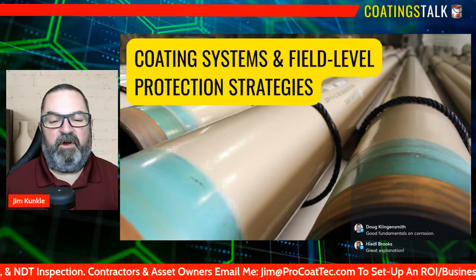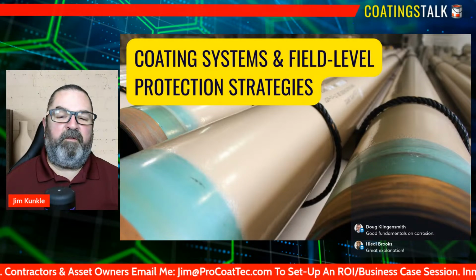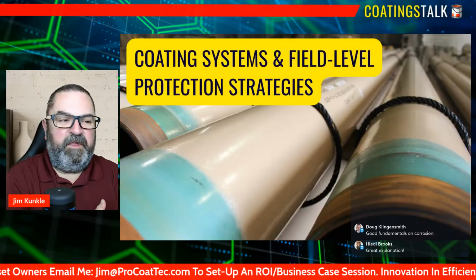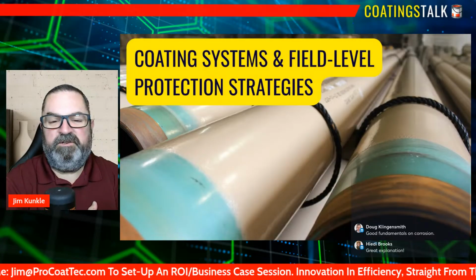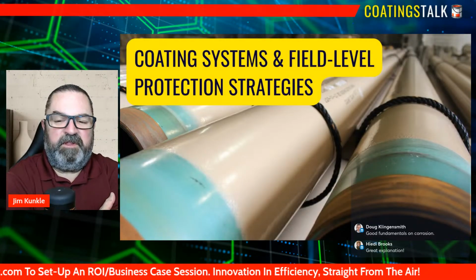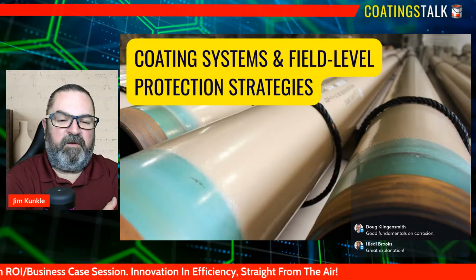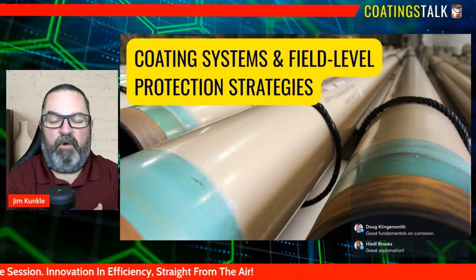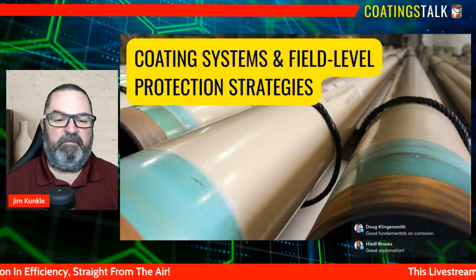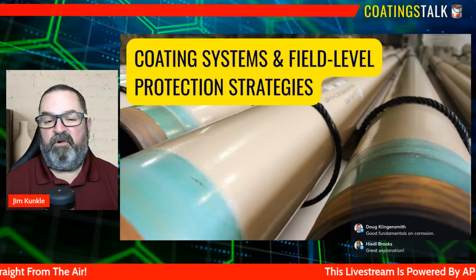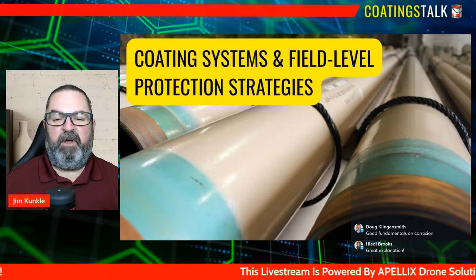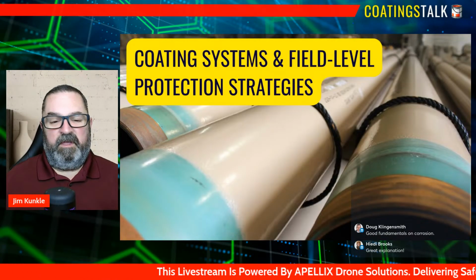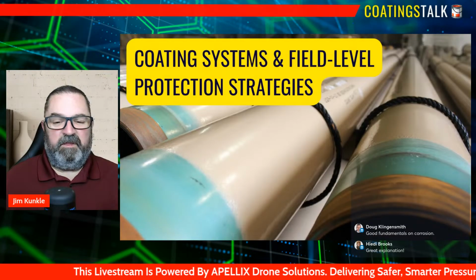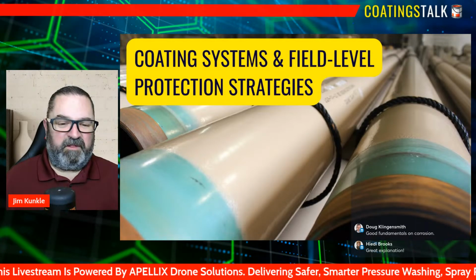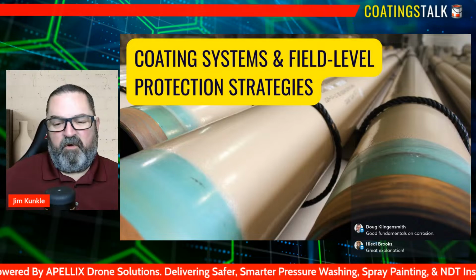Film thickness errors are another widespread challenge. Thin spots, especially on edges, welds, and complex geometries, leave the substrate vulnerable to early corrosion, while overly thick films can crack, sag, or cure improperly. Applicators may also overlook mixing and induction requirements, leading to coatings that never fully cross-link or achieve their desired performance.